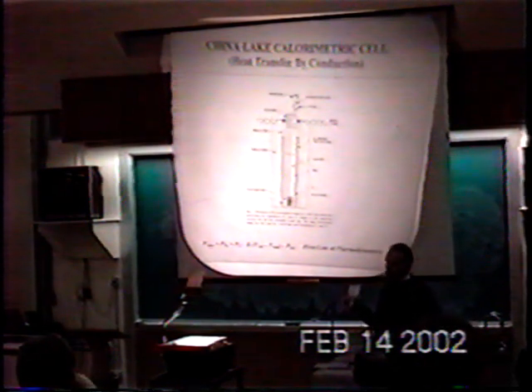This is the experimental design of the cell I use, the calorimetric cell. This is the palladium rod in the middle, the counterelectrode with the platinum spiral around it. This is the electrolyte level up here. This holds about 18 cubic centimeters, so it's not a very big cell. I packed this outer compartment with aluminum foil. The thermistors actually sit outside the cell in the aluminum foil area at 2 different positions, one lower, one higher. And then this is in a water bath, and the heat is transferred from the hotter cell here to the bath by conduction.